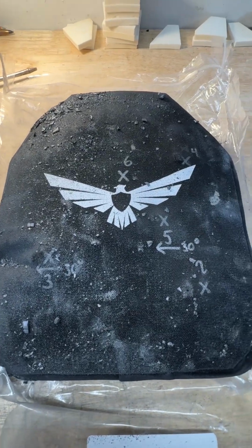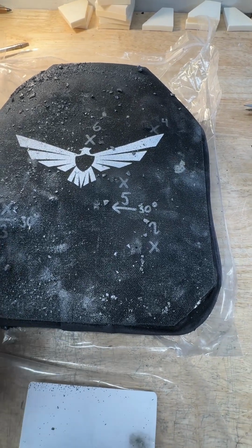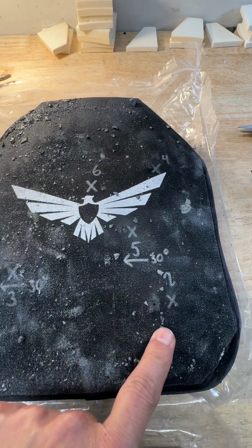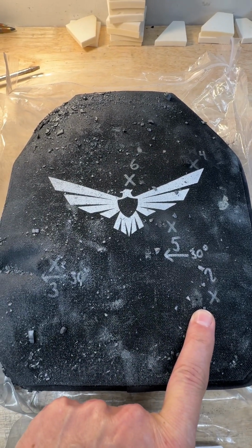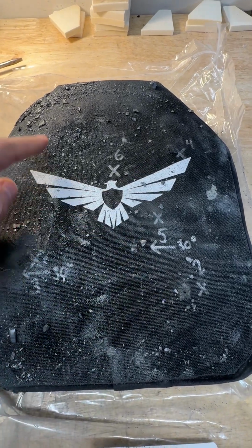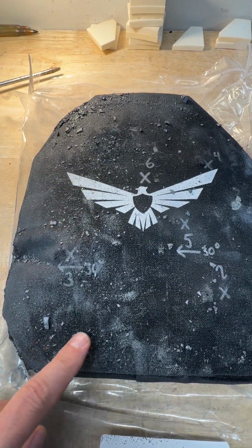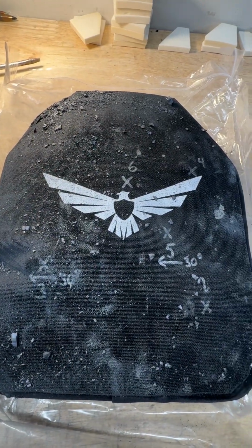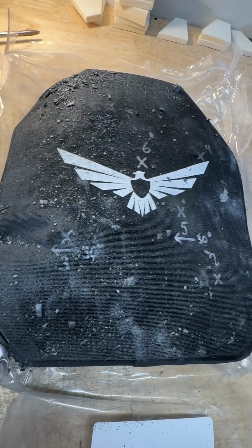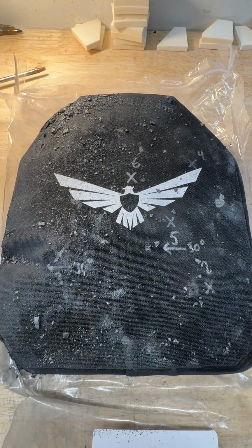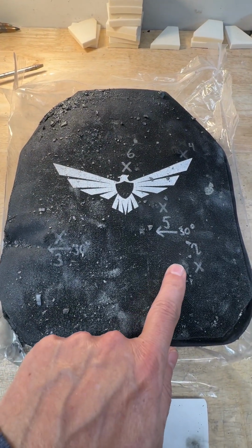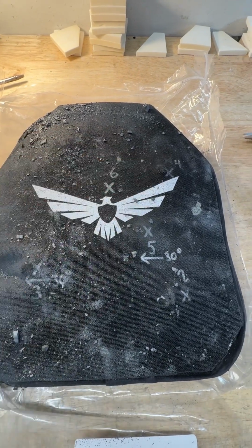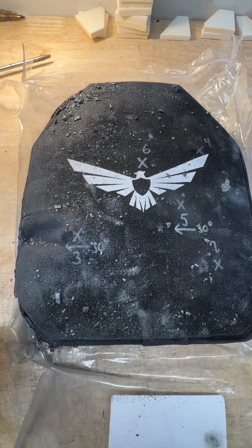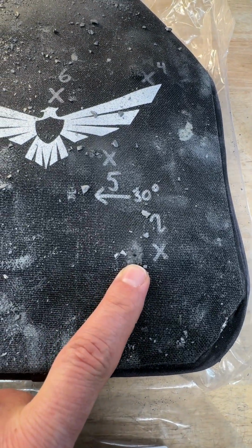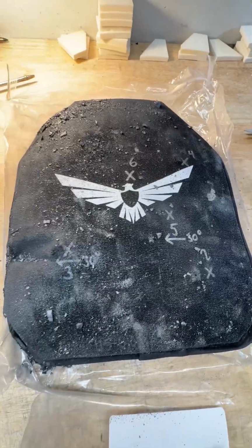First thing I see is that the shots that went in did not destroy the strike face of the ceramic, so you don't have a lot of ceramic fragmentation coming back out of the strike face once it's shot. This ceramic particle layer is just there because of the damage to the plate itself and shifting around during shipping. But you can see that the strike face cover, the crack arresting layer, did its job because you don't have a lot of open, ripped areas of fabric in the cover, and everything is nice and clean with just the projectile entry point in the strike face.